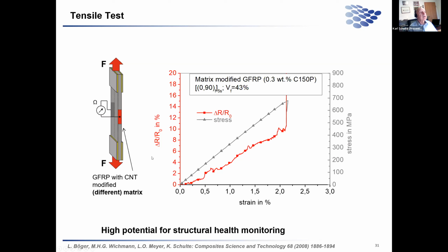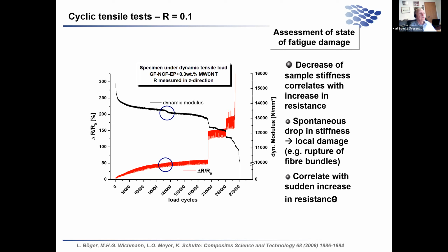If we look now at the variation in the electrical conductivity, we can see that the electrical conductivity decreases, respectively the resistance increases, following the stress strain curve. So you can use that, for instance, for monitoring in a static test, and as well for monitoring damage, for instance in a fatigue test.